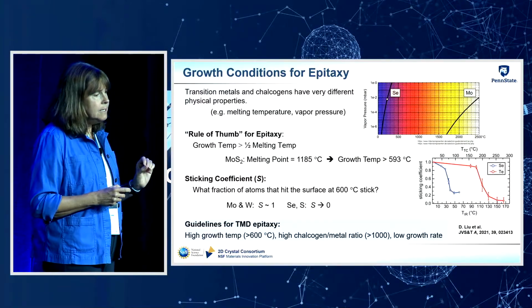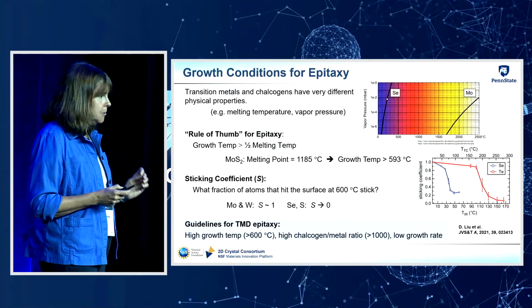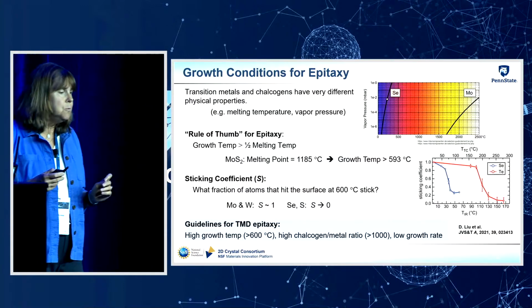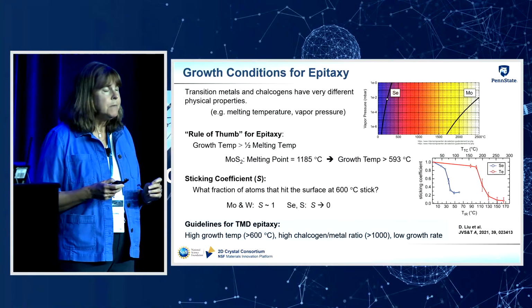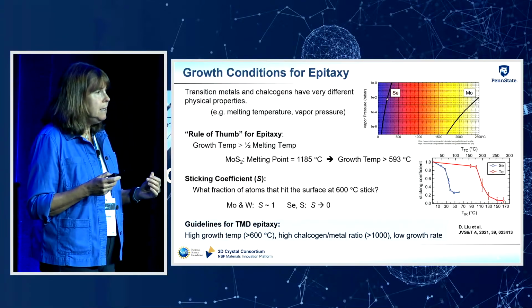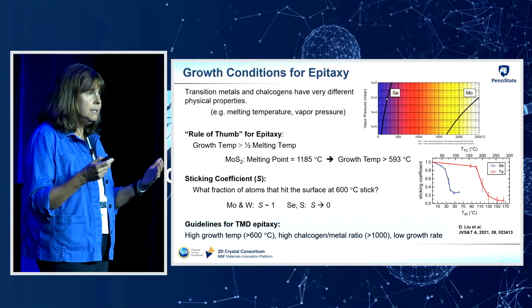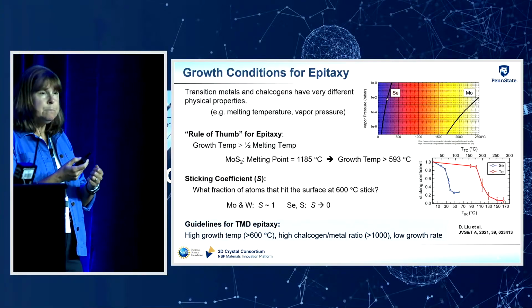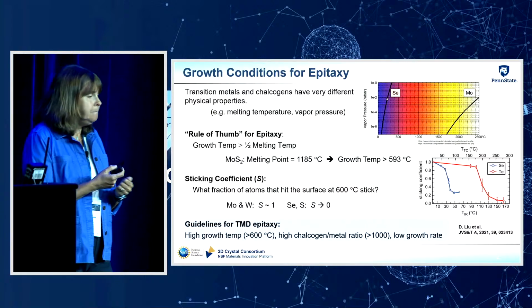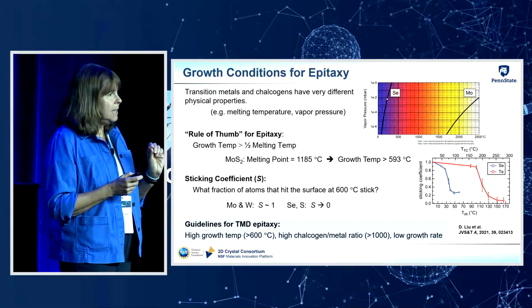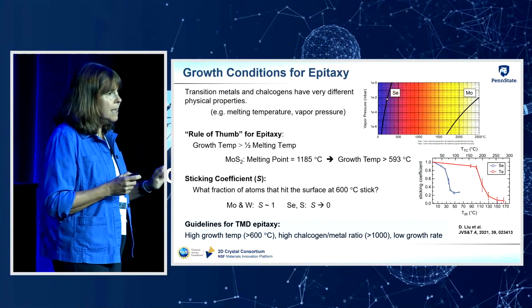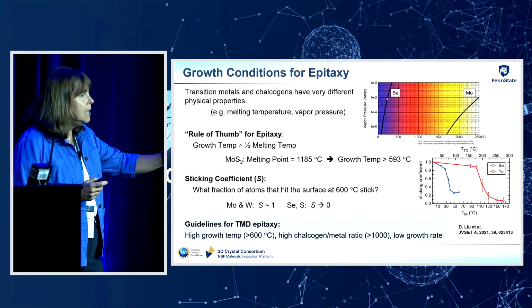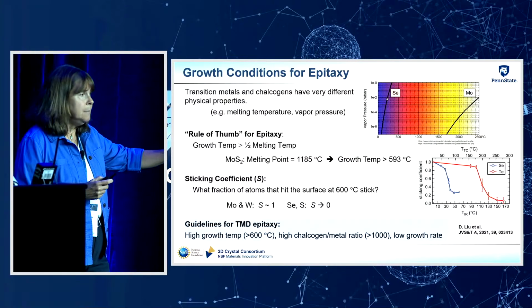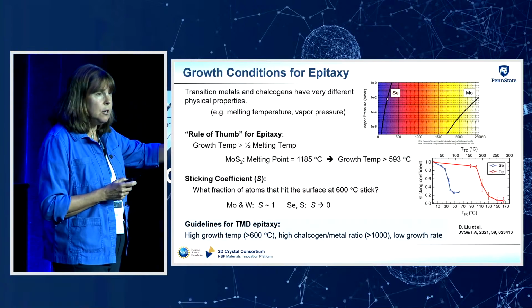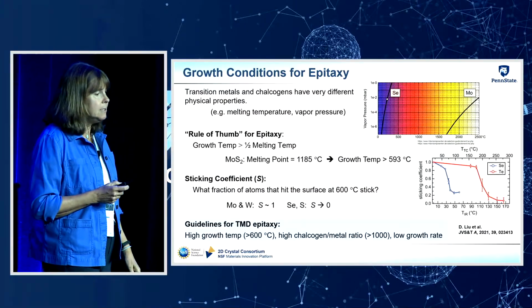Another thing that we have to consider is the growth temperature that we're going to use. And there's a general rule of thumb for epitaxy that the growth temperature should be greater than about half the melting temperature of the material. That's just based on the bond strength, right? You want the atoms to have enough energy so they can move around on the substrate surface and find a lattice location where they can incorporate in order to have an epitaxial film.